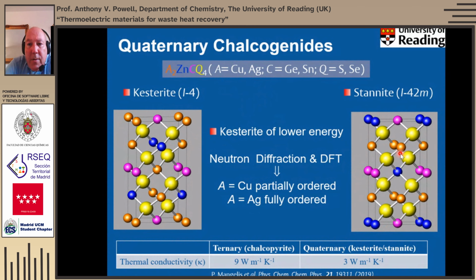These are very difficult to distinguish by X-ray diffraction, and there's a lot of confusion in the literature, and we've written a whole paper on identifying which are the stable phases for different compositions. I won't go into that lengthy story now, but just to say that a combination of neutron diffraction and DFT shows that it's the kesterite structure. When A is copper, it is partially ordered, and when A is silver, it's fully ordered.